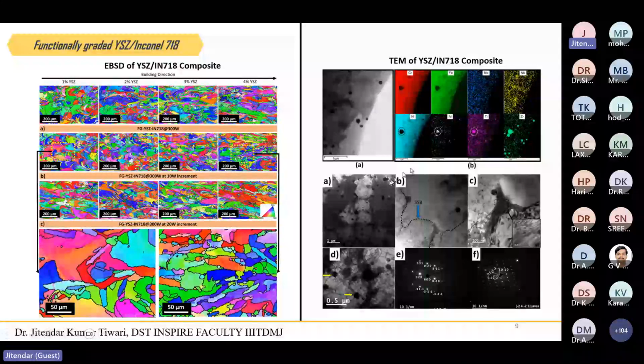So TEM Laves phases are there, and the gamma phases are there. So that is indexed with the SAD pattern. So the graded porosity case, the second one, which I mentioned already in the initial slides, that there are 3 types of pores. So lack of fusion pores, if you have less amount of energy density, and then once you increase, obviously evaporation pressure will be developed above the melt pool, and that can result in the keyhole porosity.